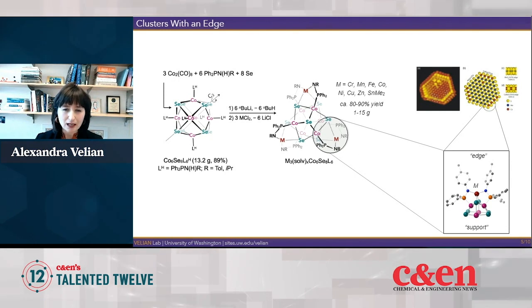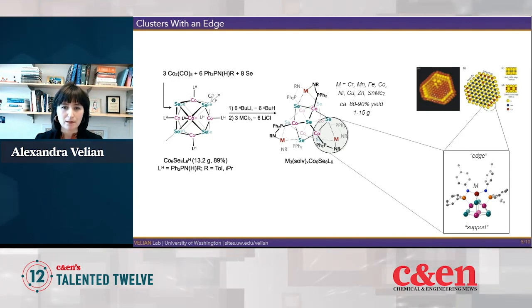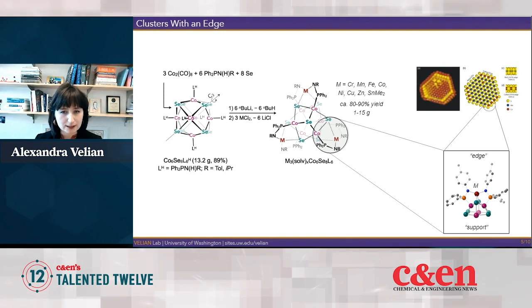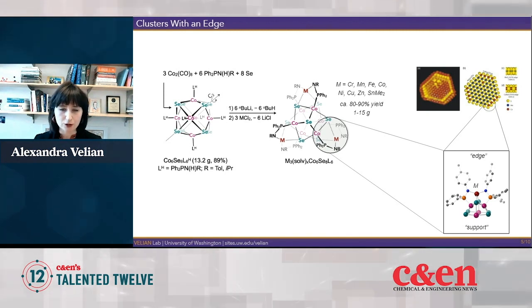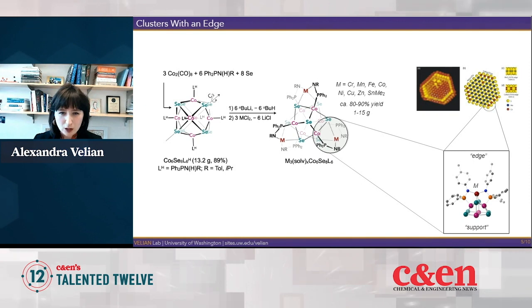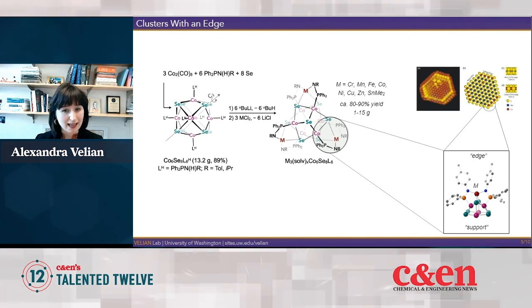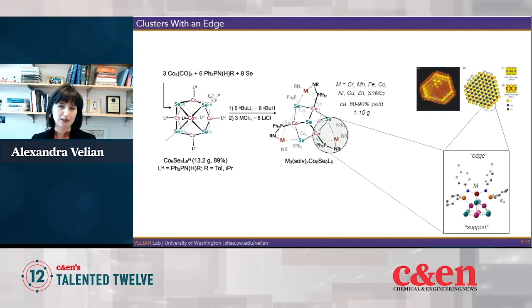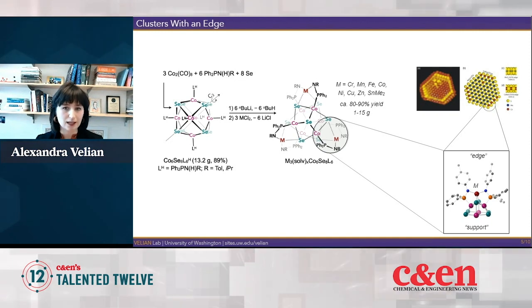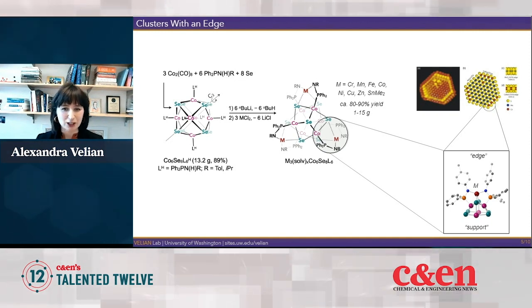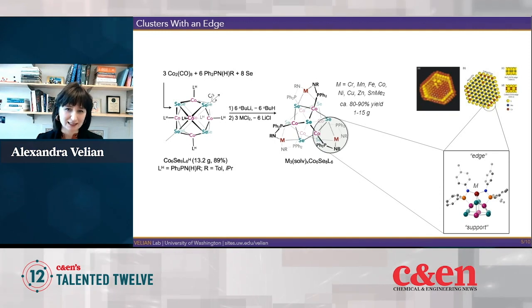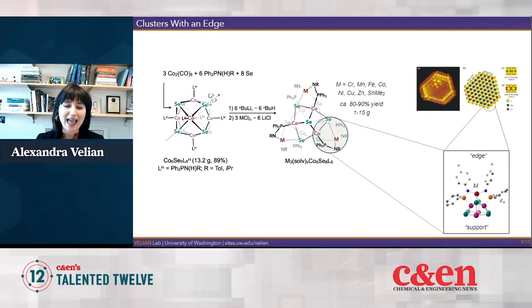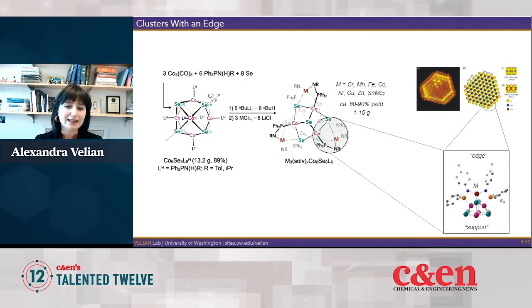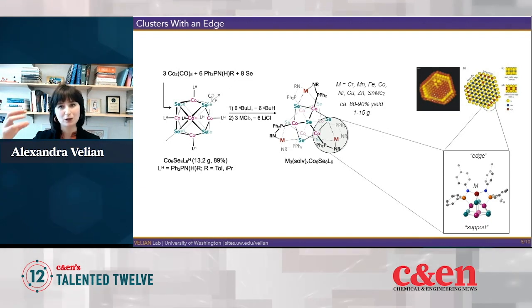So we came up with this very versatile synthesis of the clusters, essentially taking well-known, in this particular case, Co6Se8-type clusters. So this octahedron of metals, in this case cobalt, encased in a cube of chalcogens, deliberately selected to be seleniums in this case, and appended on their surface ligands that can support the secondary coordination environment. And this is important because these coordination environments can support metals on the surface.